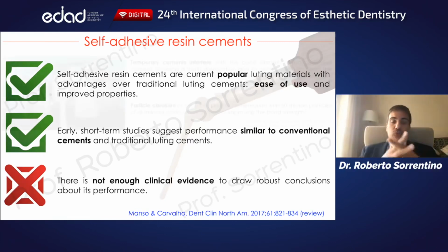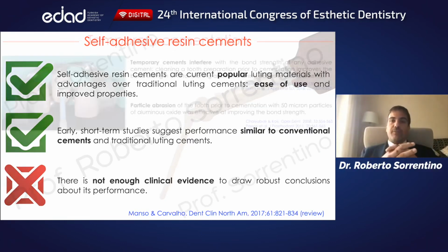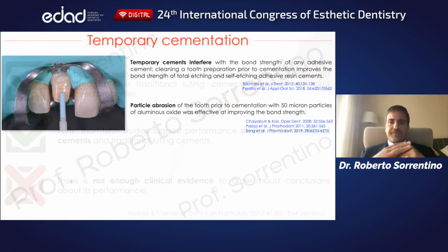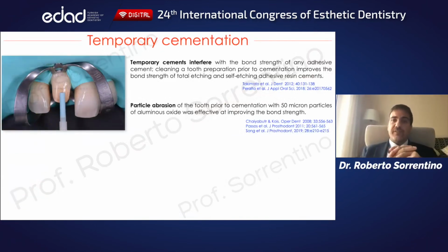Of course, to achieve the best adhesion, we have to manage clean surfaces. In particular, the remnants of provisional luting agents may interfere with the final cementation, particularly if you go for adhesive protocols, and they have to be thoroughly removed. Alumina particle abrasion proved to be the most effective procedure.